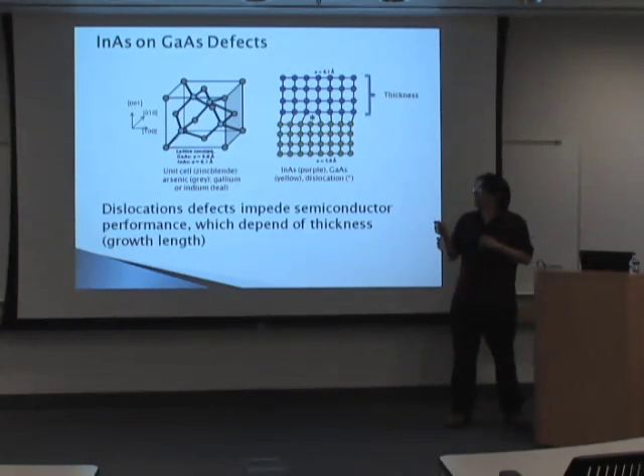And the reason why you get them is because of a slight difference in the crystals of gallium arsenide and indium arsenide. While they both share the same crystal structure, zinc blende, which is a lot like diamond, they have this length, what we call the lattice constant. It's different for indium arsenide and gallium arsenide. Because of this mismatch, this introduces strain when you grow indium arsenide on your gallium arsenide substrate. When there's too much strain, these dislocation defects appear on your surface, and you see this as roughness, and it will decrease the performance of your semiconductors.